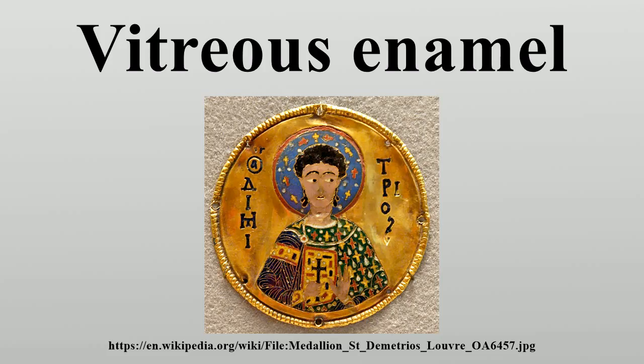The frit in the ground coat contains smelted-in cobalt or nickel oxide as well as other transition metal oxides to catalyze the enamel-steel bonding reactions. During firing of the enamel at between 760 to 895 degrees Celsius, iron oxide scale first forms on the steel. The molten enamel dissolves the iron oxide and precipitates cobalt and nickel. The iron acts as the anode in an electrogalvanic reaction in which the iron is again oxidized, dissolved by the glass, and oxidized again with the available cobalt and nickel, limiting the reaction. Finally, the surface becomes roughened with the glass anchored into the holes.